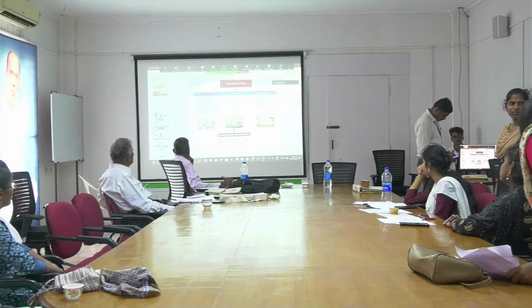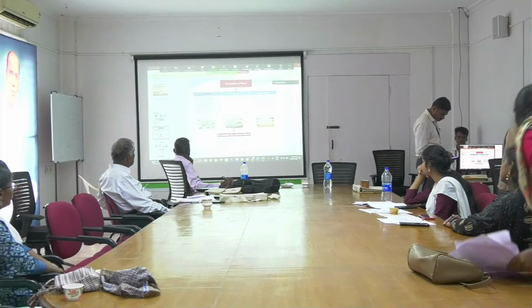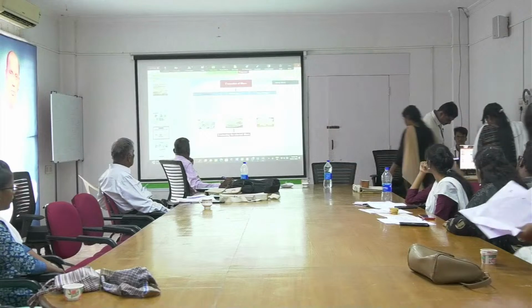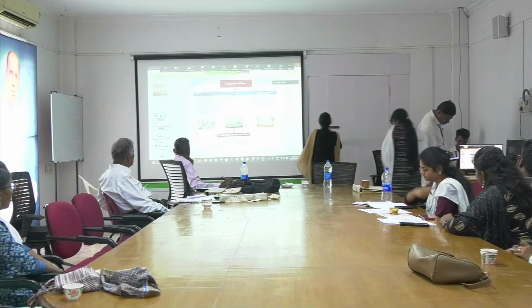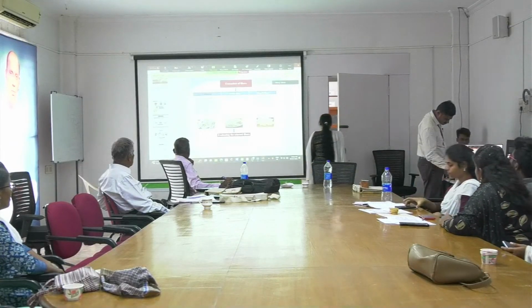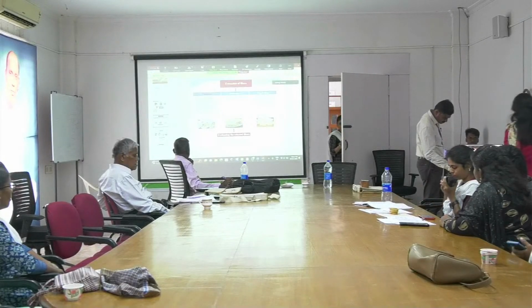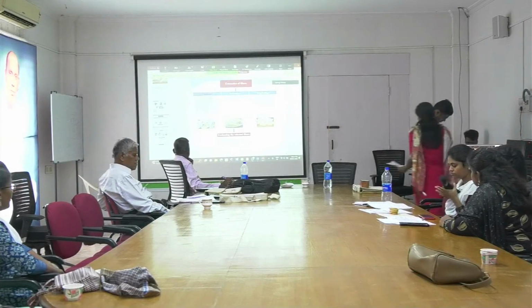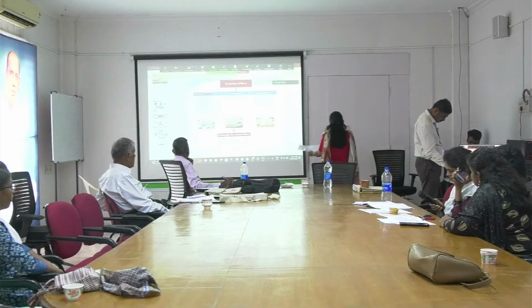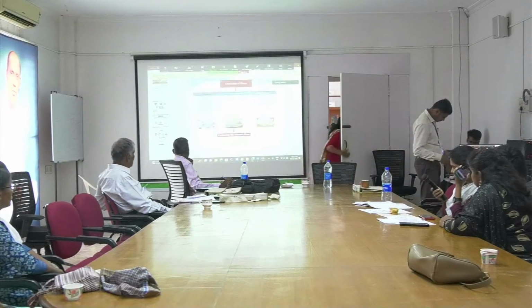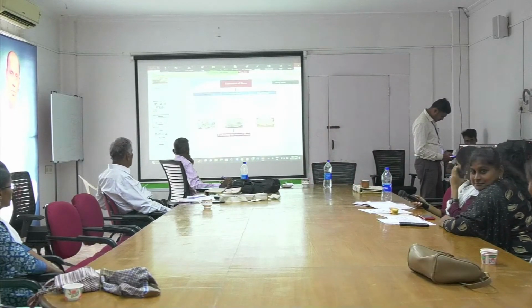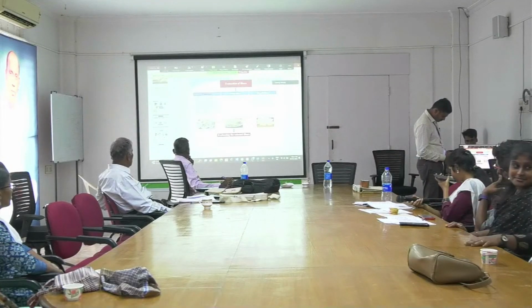Extraction of the fiber. The calotropis is collected from the roadside of Tondamuthal Road. The fibers are manually removed from the cluster and dried at room temperature. After drying, they are washed in plain water to remove foreign substances such as dirt and contamination. Once washed, they are dried again at the same room temperature to facilitate proper web formation without any flying.